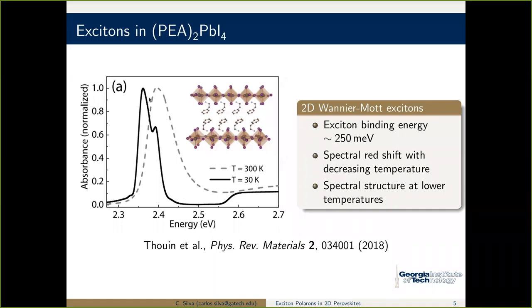So let's look at the low temperature one, because that's clear. We see very clearly defined where the bandgap is. Here's the band-to-band transition. Downstream, this main peak, 250 to 300 millielectron volts. Let's just take that as the exciton binding energy, a very strongly bound exciton. But as we cool it, we see structure appearing. Now we don't have a single resonance, but in fact we see at least two. And in fact it's not only two. I'll show you in a minute. And so what is the structure?